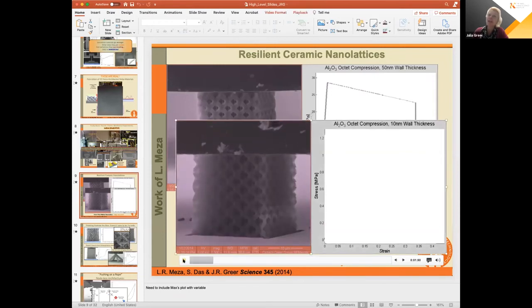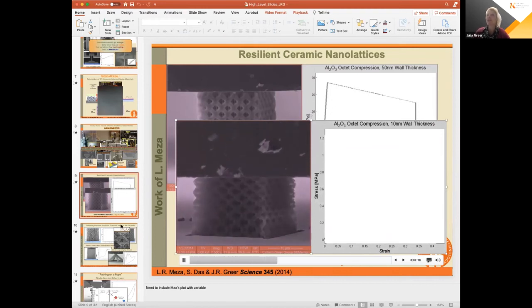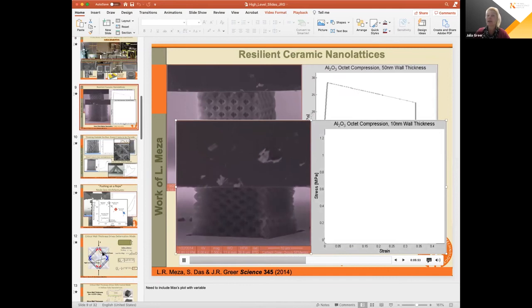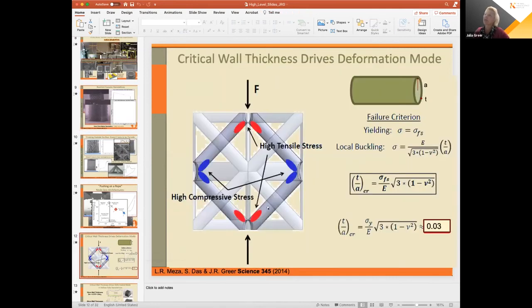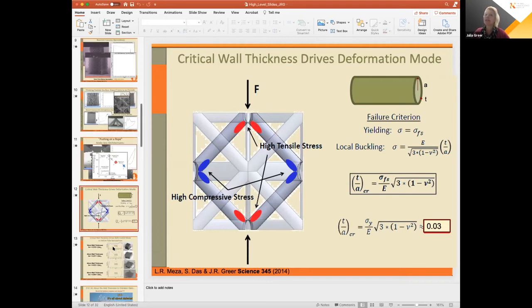You can see that locally, there are regions of tensile stresses and compressive stresses, as well as wrinkling. So all the phenomena that you're bringing up are effectively mechanical. The level of deformation is not quite at the atomic bond level, but we're certainly accumulating some damage. In fact, some microcracks can even form when the stress concentrations at these local spots, especially at the nodes, exceed the fracture strength of the material. Now, the nice thing is that they're subcritical. And that's what gives rise to this less than ideal scaling.